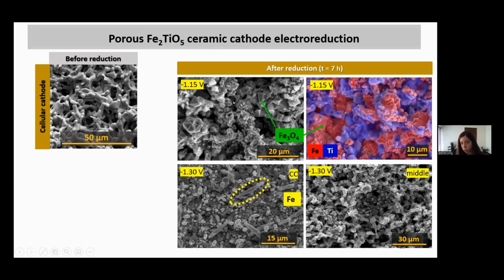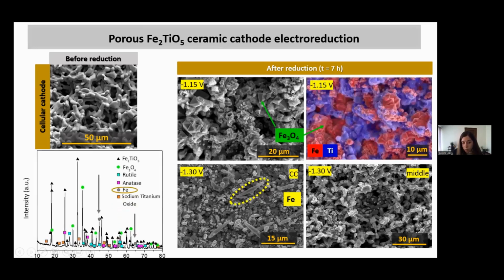It's also possible to see these crystals. At first, we thought it was metallic iron. However, it is not. It is only magnetite. So it seems like we didn't succeed to obtain metallic iron at this cathodic polarization. Because of this, we increased the polarization to -1.30. And here we do have metallic iron. These are the dendrites of metallic iron, and we observe them only at the current collector.